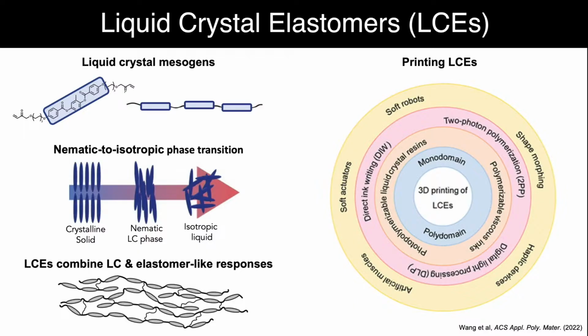And of course, there are other methods. Some of these methods, absent a magnetic field, don't encode the directional alignment of these rigid mesogens. As you'll see, that's quite important for many of the devices shown here, which include shape-morphing architectures, robots, actuators, and artificial muscles. I don't even want to highlight haptic devices here because I think the time scale for transformations of liquid crystal elastomers is far too long for haptic interfaces. So in the haptic device space, we've been focusing on dielectric elastomer actuators. That is a much faster response.